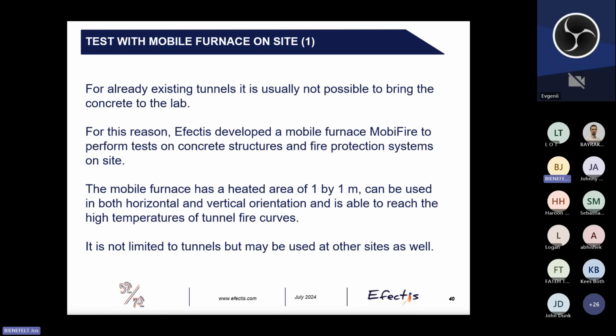Sometimes it's not possible to perform a test at our lab, and then we can go with our mobile furnace to the actual concrete tunnel structure. So for that reason, Efectis developed a mobile furnace. We have called it MobiFire, and we can perform tests on the wall or the ceiling of an actual tunnel.